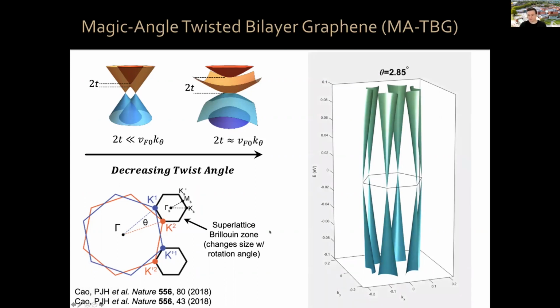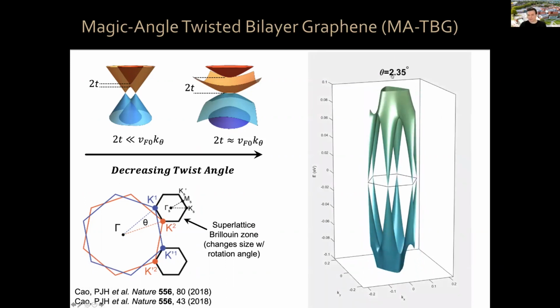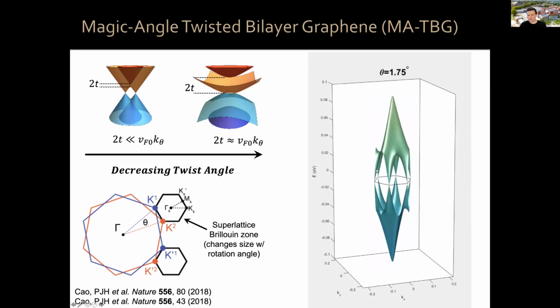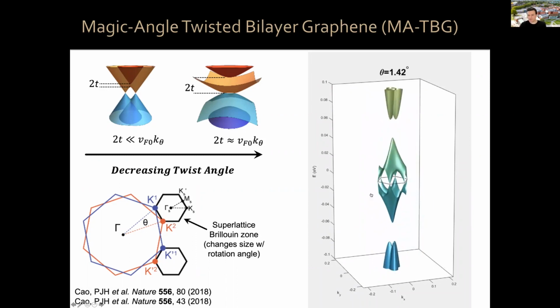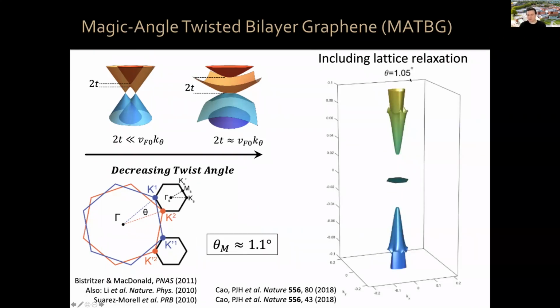You can see how as the angle decreases, this electronic structure, which before looked just like graphene, gets reconstructed, and you have this very flat band at about 1.1 degrees. This includes lattice relaxation, although the angle keeps changing depending on the model, but you have this very flat electronic structure there. Now let me put back my laser pointer.